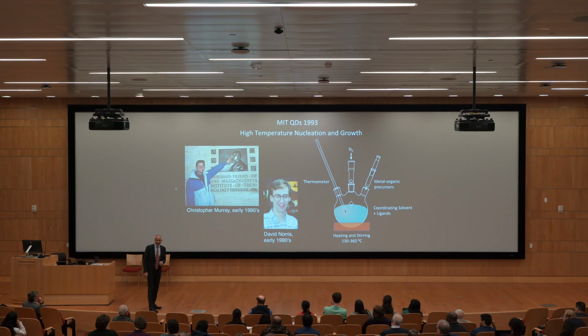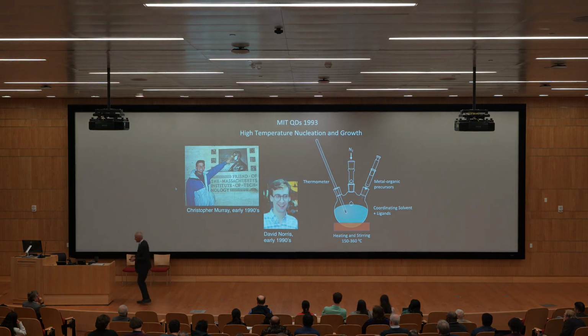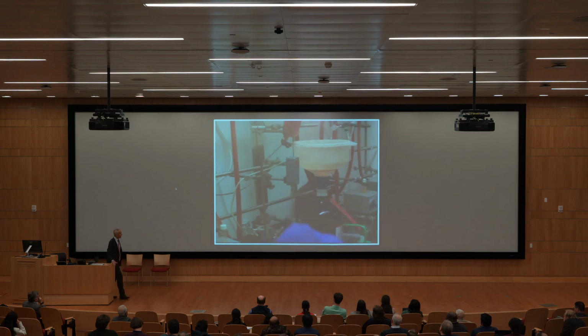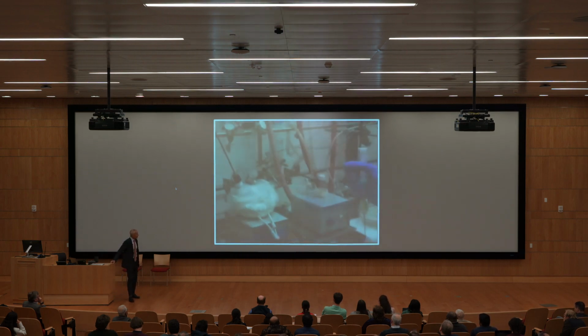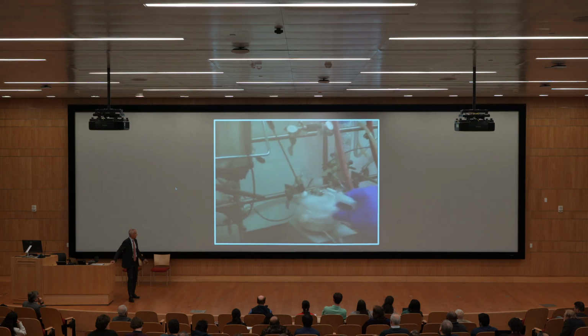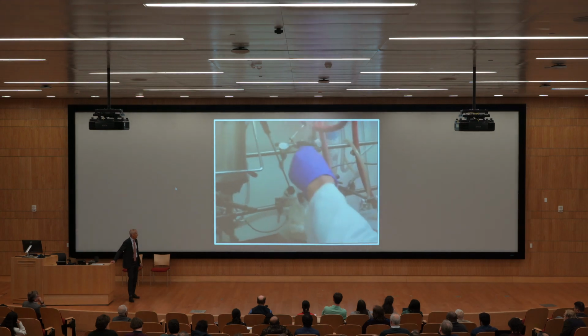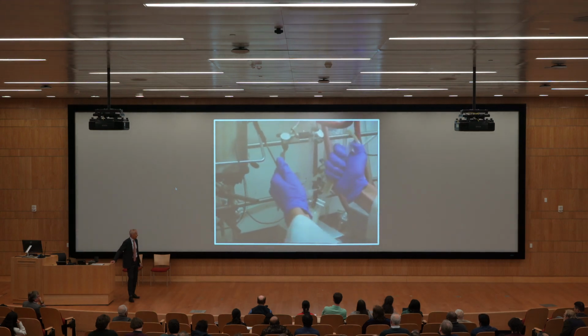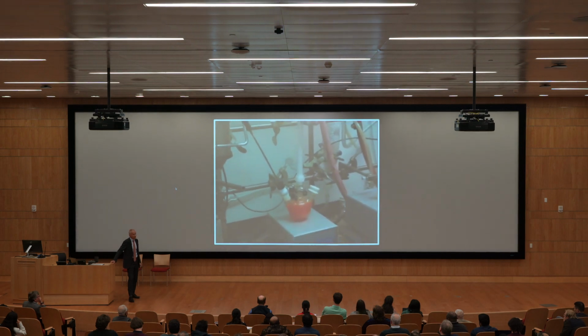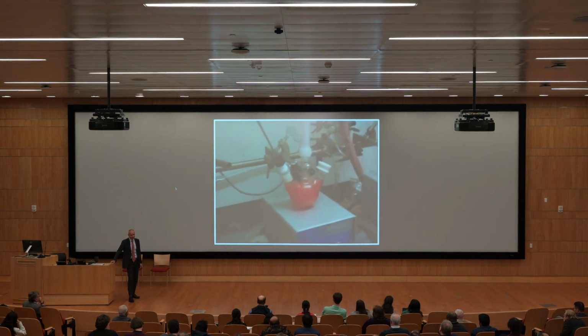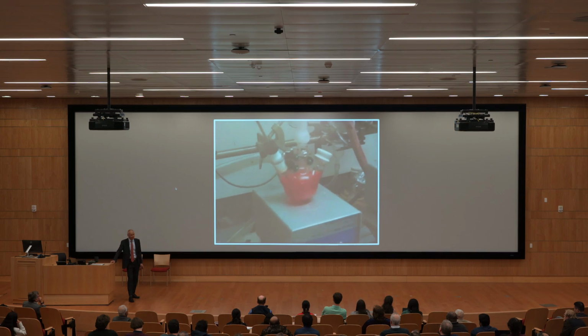300 degrees Celsius. We can watch it with our eyes because we're looking at color. When it has the size that we want, we just turn the heat off for the rest to grow. A video of what it looks like here. So there's the precursors in the syringe. The flask is at 300 degrees Celsius. Quick injection. The color that you see is from nanometer-sized seeds of cadmium selenide at high temperature.